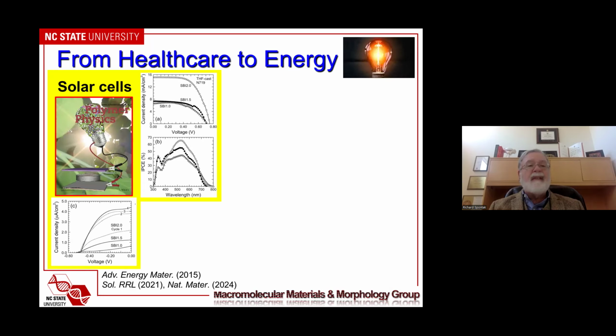We can make simple ones that mimic leaves, and so current densities are low, on the order of microamps per square centimeter, and efficiencies that are laughably low, but they do mimic leaves. If we wanted to make something that was more commercially relevant, we could make dye-sensitized solar cells, which is what you see here. Now, current densities are in the milliamp per square centimeter range. We're looking at fill factors of about 70%, and we're looking at efficiencies of about 7%. And that's non-optimized. In addition to that, the incident photon conversion efficiency that you see here indicates that we're collecting photons over a very broad wavelength range.